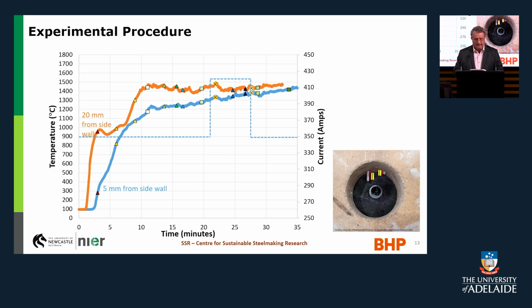Okay, so we start with a cold charge, fill up the reactor volume, strike up that arc, and find that we get a molten pool very rapidly, within 10 minutes. And then the temperature stabilises a little bit, and we're able to do some extra top feeding, which in some ways simulates a real-scale electric smelting furnace. And we're able to take metal and slag samples in situ as we progress through a run, okay? So we're doing all these things. And it's an exciting experiment, and we've done about 60 of them now, so we're getting good at it.